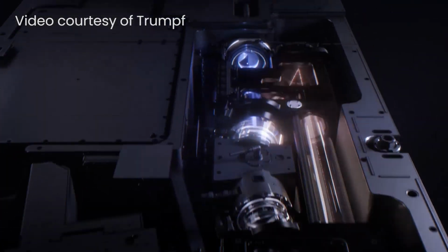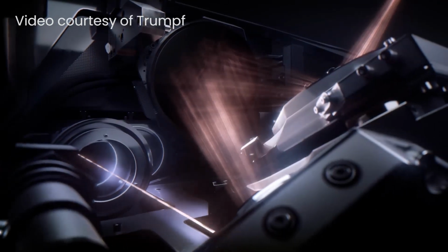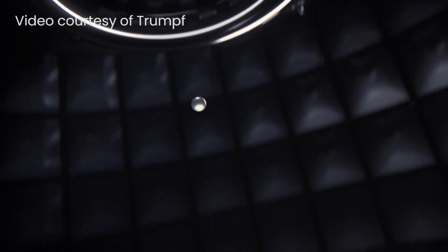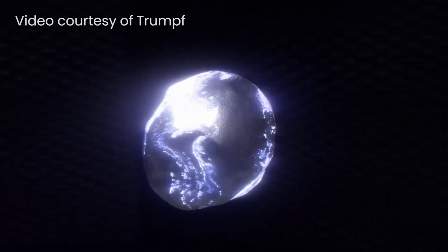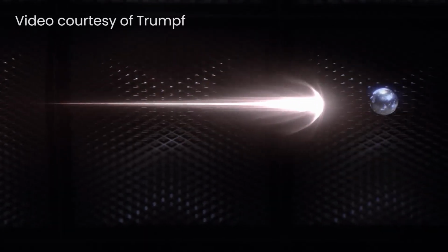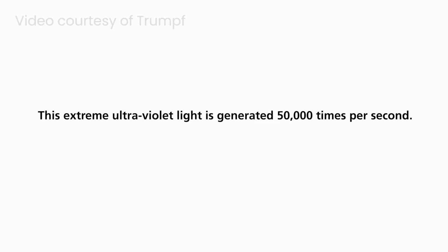Also, consider the optics by Zeiss to shape and direct the EUV light. It's one thing to specify the surface quality to lambda over 10 when the wavelength is 632 nanometers, but quite another when it's 13.5 nanometers. In fact, the mirrors are made with a surface roughness of 0.1 nanometers, which is about the diameter of a hydrogen atom. While we can talk about many more technological feats, I think it's safe to say that EUV photolithography is a quintessential application of photonics.